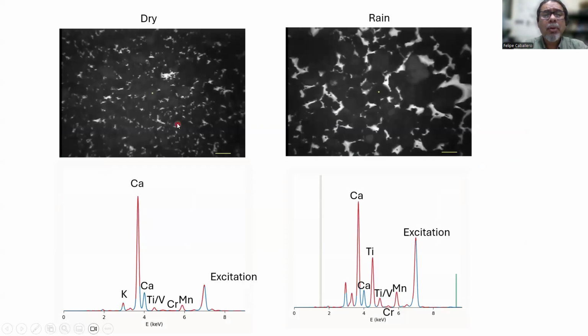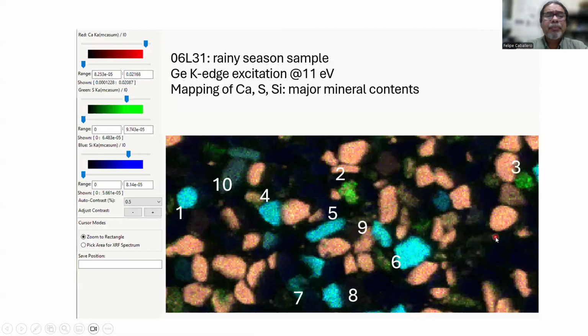So these are the maps of the samples, the microscopic maps. So we can see here the pebbles around all the sample here and the rainy one. The general X-ray fluorescence maps, where we can observe calcium, titanium, vanadium, manganese, and chromium, and the excitation peak at 7 kiloelectron volts that is able to excite the previous elements. So we can perform a quantitative analysis considering the relative sizes of the peaks. And then we do the compositional map of one selected region. Particularly here, we are mapping calcium, sulfur, and silicon that are among the main mineral contents. Remember the X-ray diffraction, we saw quartz, we saw calcite, we saw gypsum that contain these 3 elements.